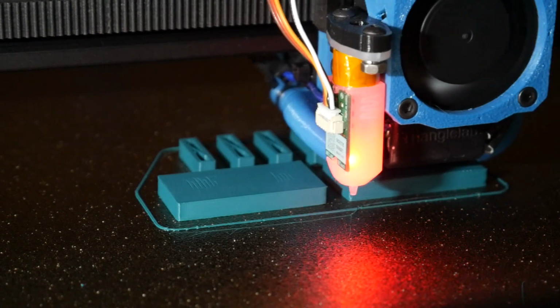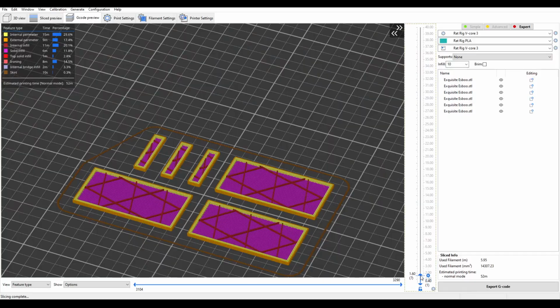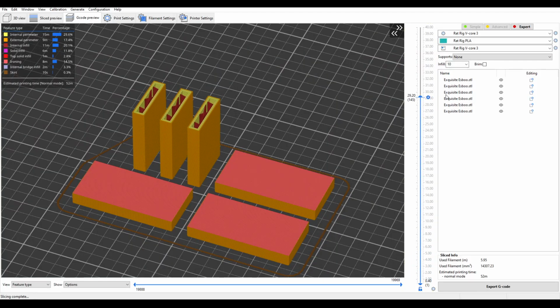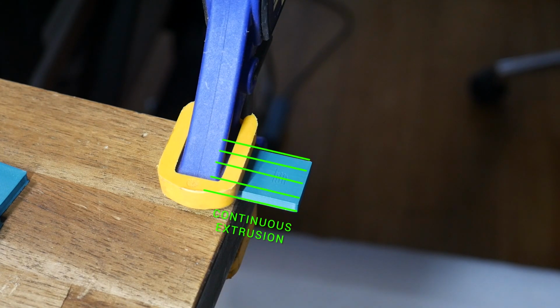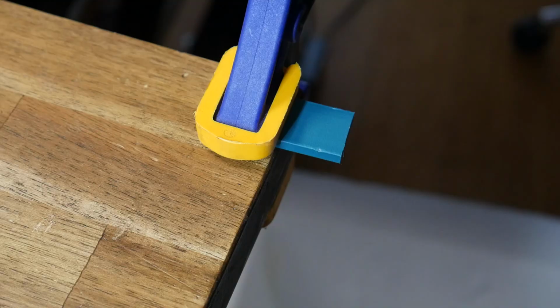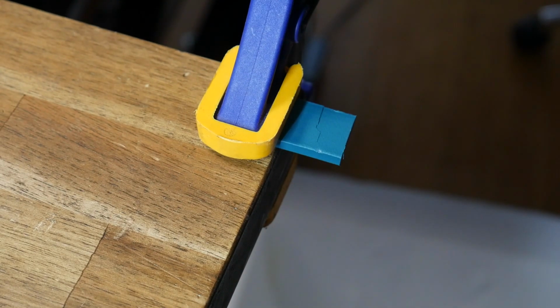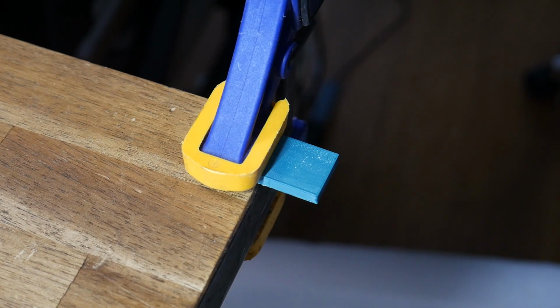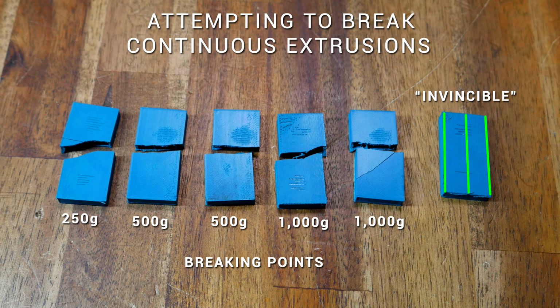So how will our 3D printed test pieces fare? The first thing to point out is that they're printed nearly hollow to remove the influence of infill strength. We start again with our continuous extrusion, going from left to right, and we keep increasing the weight until we have a crack or an abysmal failure. The strength of these parts varied, with the strongest being able to withstand 1 kilogram. Our low layer died with a 250 gram impact, 2 others broke with half a kilogram, the next 2 broke at 1 kilogram, and then we have our invincible test piece, which I couldn't seem to break.